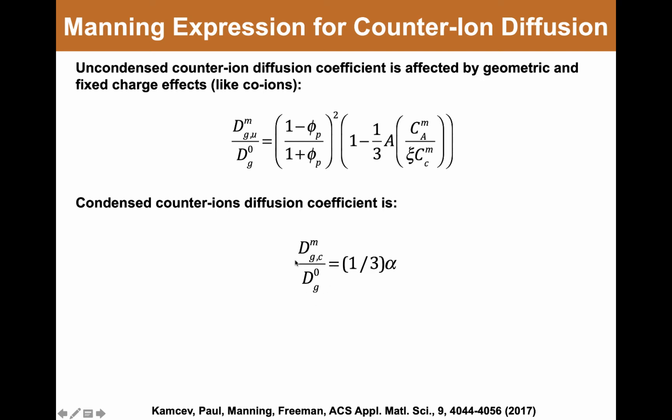And so one thing we should mention is that the ion diffusion coefficients in the membrane are always slower than they are in solution. The tortuosity effect accounts for most of that, the electrostatic effect for a little, but the ions always move much slower through the membranes than they do through free solution.